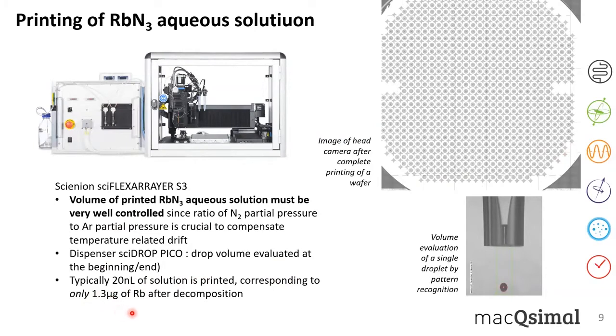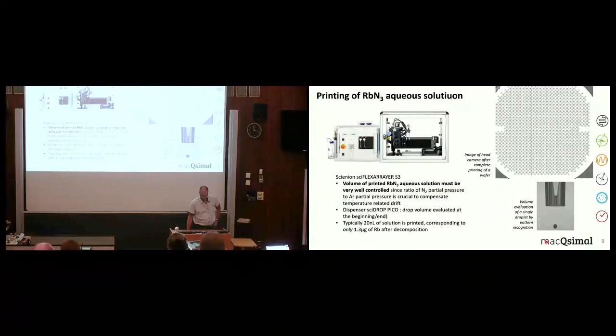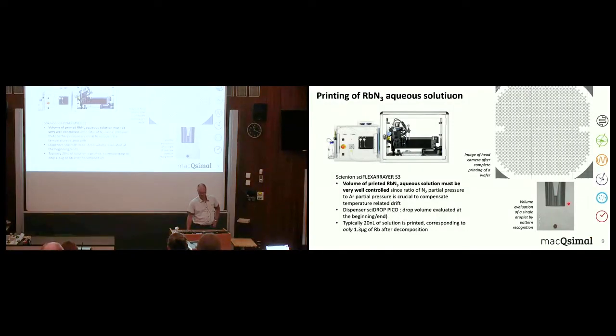Also, to control the quality of the printing, some test droplets are printed at the beginning and at the end of the process, and by pattern recognition they can calculate the volume of the droplet. It is quite stable in time, so there's no big difference between the beginning of the printing and the end of the printing.